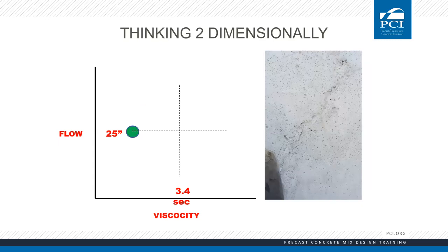Let's consider another example: a reduction of viscosity with no change in slump. The slump is still good, but we have less viscosity. If you're only testing flow, you would never catch this problem because you're not testing the T20 — you wouldn't see the change in viscosity. The product shows what we call sand trail. This happens when we have a high sand content mix that is bleeding. When water demand increases, whether from heat or a change in materials, we react with an increase in high-range water reducer until the mix is unstable. The bleed water is often not noticeable until well after we've finished the product. The increase in HRWR maintained the right flow but adversely affected the viscosity. A better fix would be to make an adjustment to the fine aggregate.